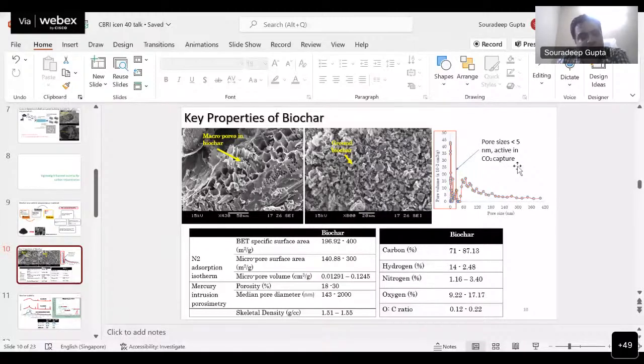The properties of biochar will vary quite a bit depending on the feedstock and how we make it. So I'm giving some range of these numbers corresponding to each property. The surface area can be very high, varying between 200 square meters per gram to 400 square meters per gram. And the higher the surface area, the higher the affinity for CO2 capture. Similarly, the carbon content of biochar will also depend on the carbon content of the feedstock, and it can vary between 70 to 90%. And the oxygen to carbon ratio, which is a measure of stability, can vary between 0.12 to 0.22.